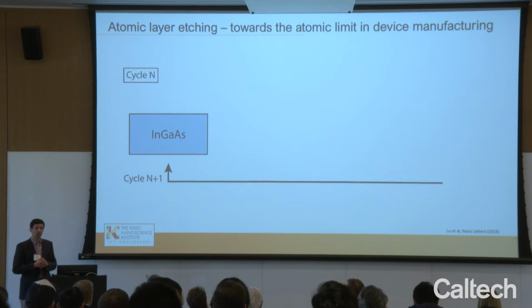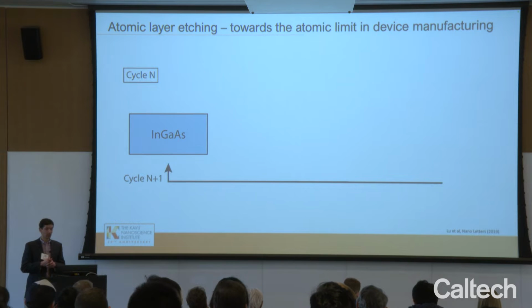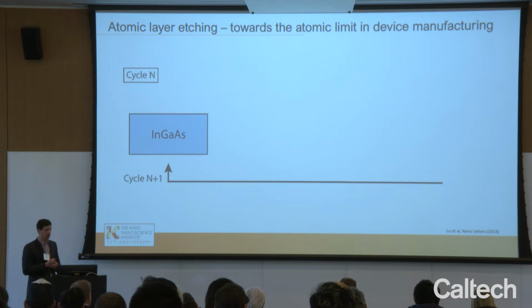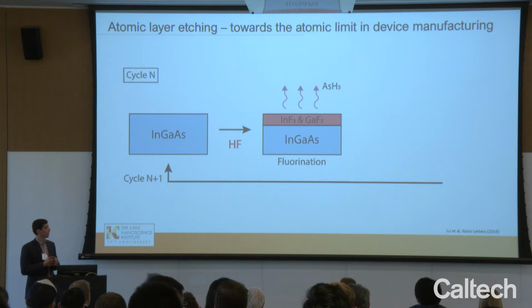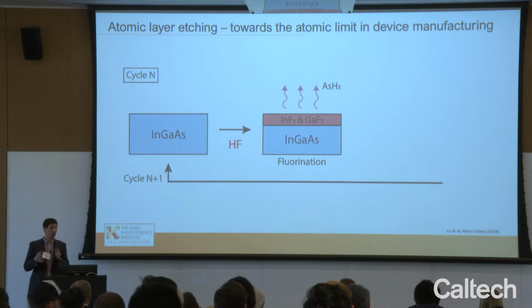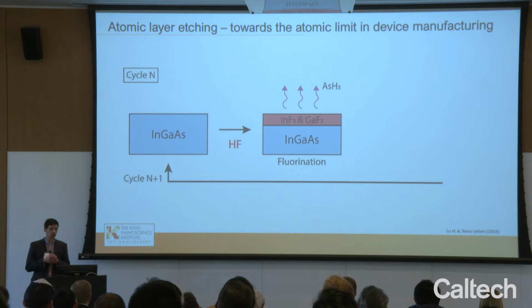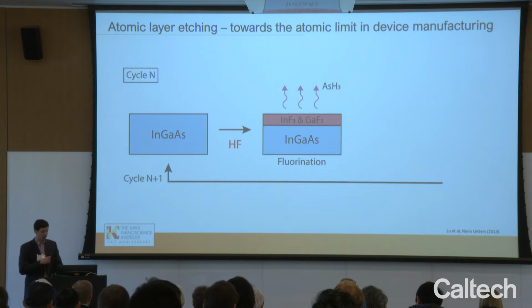And remarkably, there is a method that can do this, which is an emerging method in nanoscience and microfabrication. This is known as atomic layer etching, and it works in a cyclic fashion. You start with your material that you want to etch. You expose it to a gas or a precursor or some type of molecule, and by the way that you've carefully chosen the chemistry, there's a self-limiting surface chemical reaction that occurs. That means this chemical reacts only with the surface, but once it has modified the surface, it stops. And that only affects the top atomic plane of your material.